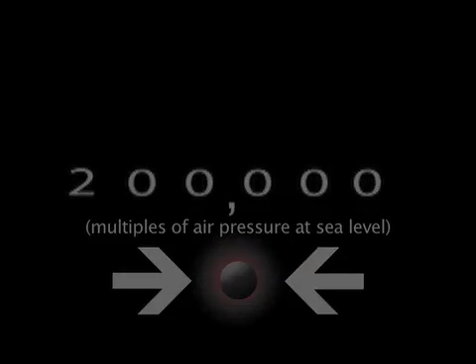In the models, superconductivity set in at pressures between roughly 100,000 to 200,000 times the atmospheric pressure at sea level or 10 to 20 gigapascals. This is an order of magnitude lower than the pressures for related compounds that bind with four hydrogens instead of three.